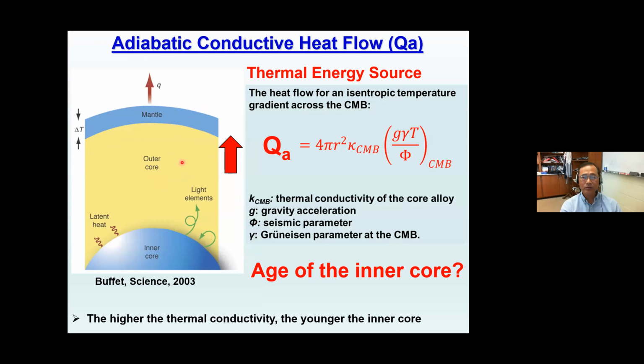All right, so if we now look at that thermal energy source, QA here, this is related to these parameters here, and the key parameter is really the thermal conductivity of the core alloy. It's also related to the Grüneisen parameter and seismic parameter. These values we know relatively well, but the thermal conductivity of the constituent alloy is highly uncertain. And let's say if this value is really, really large, say 200 watts per meter per Kelvin, what could happen is that the core has very high thermal conductivity, and so you actually have a very young inner core. So the inner core actually grows relatively fast.